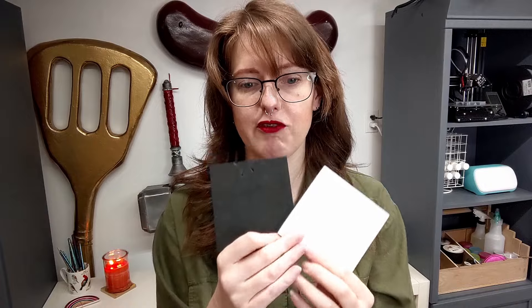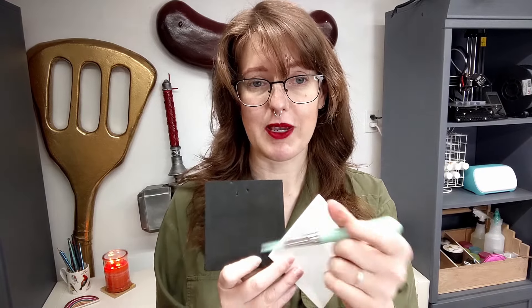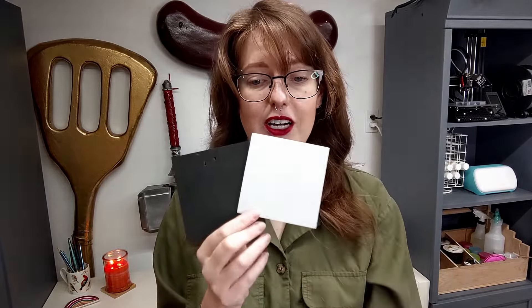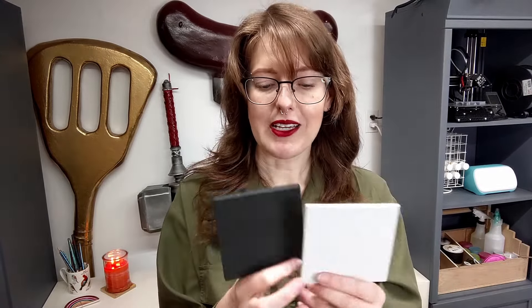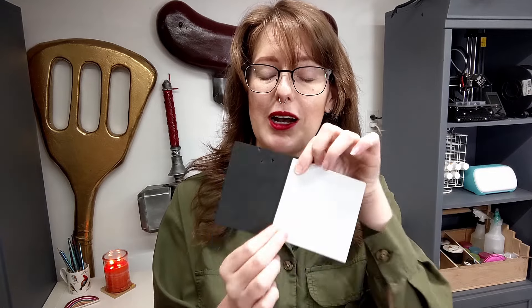Contact cement can take a little bit of practice to get really comfortable with and get the best results. That's because you have to let the contact cement gas off before you connect the pieces. So the way you use it: say I'm trying to connect these two pieces of EVA foam — I would take my silicone brush, get contact cement on it, brush on a very thin layer, then brush contact cement on the other piece. Now you have two pieces with contact cement on them. At that point, you let them sit and let them dry. When they're ready, it'll be very slightly tacky but won't have much sheen to it anymore. At that point, press the objects together and apply some pressure, and they're stuck together.